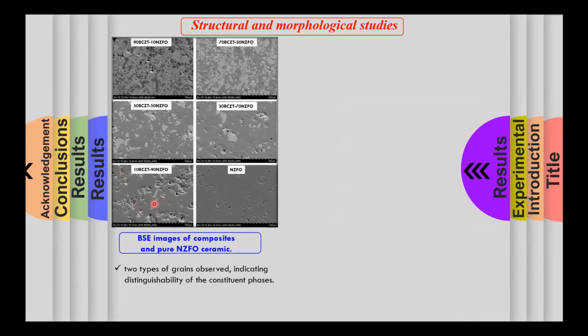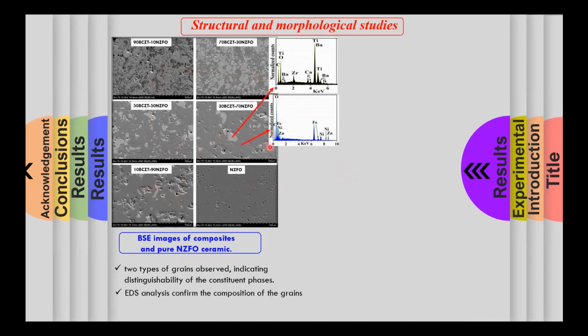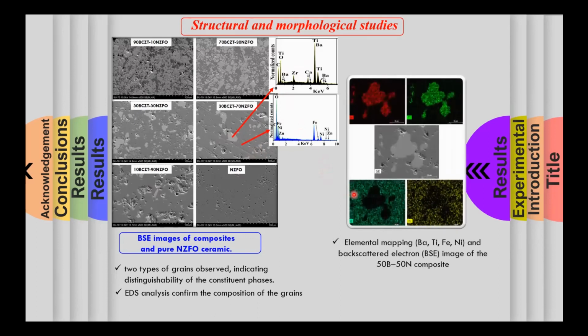Here we see the backscattered electron images of the polished surfaces of the composites, along with the parent nickel zinc ferrite. Scattered pores and pullouts resulting from the polishing are also noticeable. In all the composites, we see regions of light and dark contrast, and the composition of the respective regions was analyzed by EDS, that is energy dispersive X-ray spectroscopy, which confirmed that the lighter regions correspond to the piezoelectric BCZT phase, while the darker ones belong to the magnetic nickel zinc ferrite phase. Further verification was provided by the elemental mapping that identified the barium and titanium elements in the lighter zone, while the iron and nickel in the darker regions.